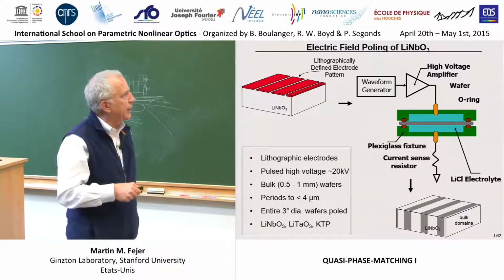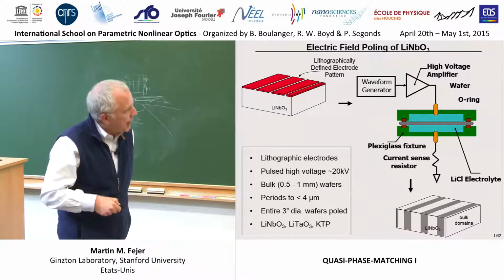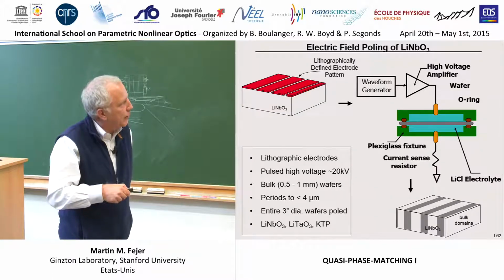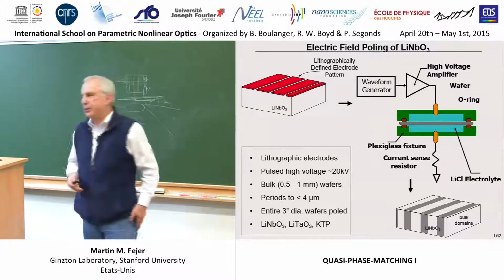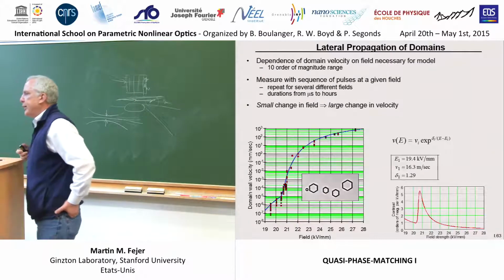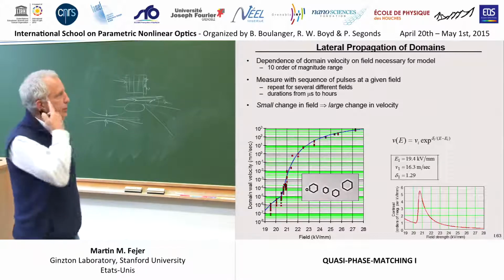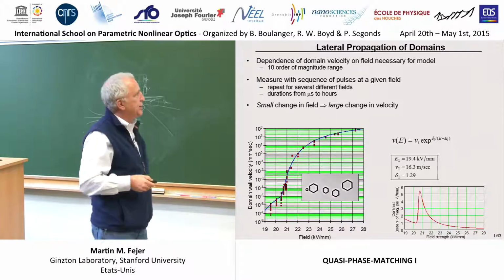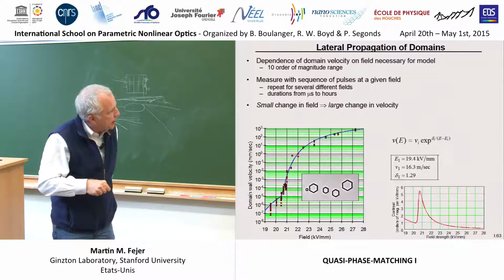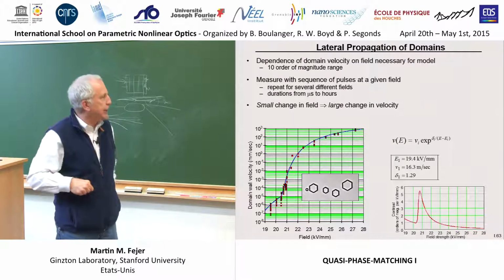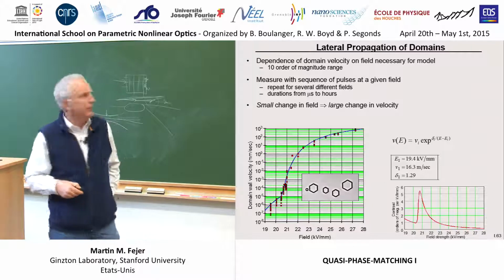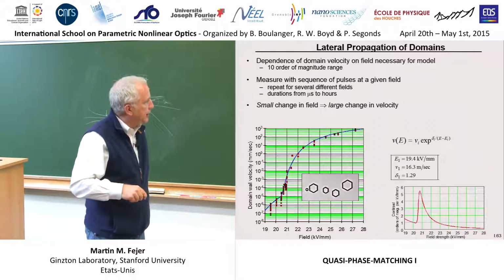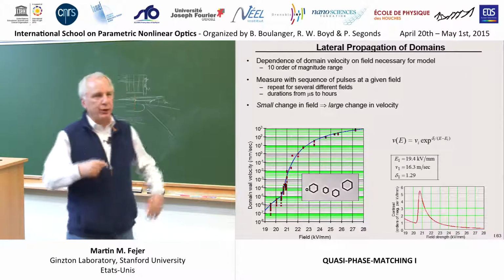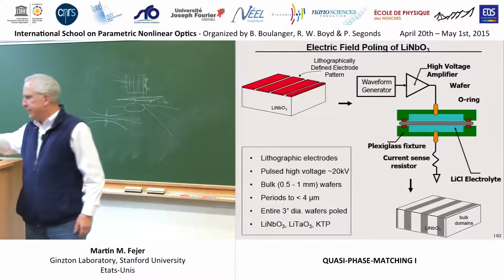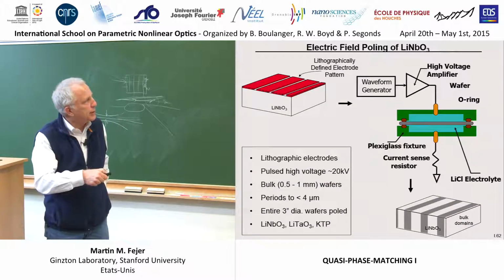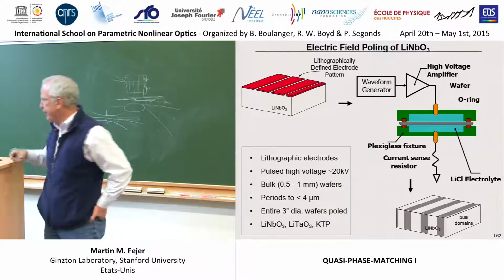And if you apply the right high voltage to this thing, you end up getting the domains forming through the thickness of the wafer and then stopping at some desired size. So why do they do that? Well, an important measurement that Greg made was what is the velocity of growth of these domain walls as a function of the applied electric field. And so this is going from 19 kilovolts per millimeter to 28 kilovolts per millimeter. That's the voltage applied just across the wafer.